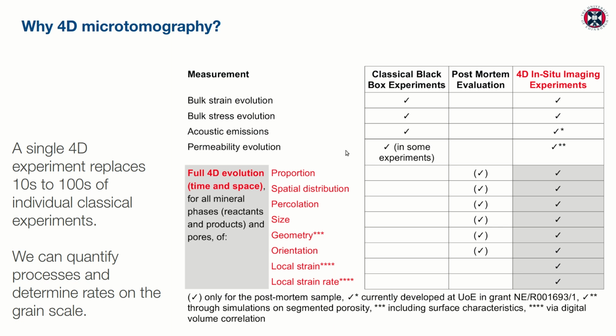Usually, once an experiment is completed in one of these apparatus, we extract the sample and then we can do a post-mortem evaluation, which gives us access to a couple more parameters, including, for example, the proportion of minerals that partook in deformation processes or metamorphic reactions, their spatial distribution, the percolation size, geometry, the orientation. However, of course, all of this can only be sort of determined for a post-experimental state, right? That's one snapshot in time that we take after the actual experiment and after the processes we're interested in ceased to be active.